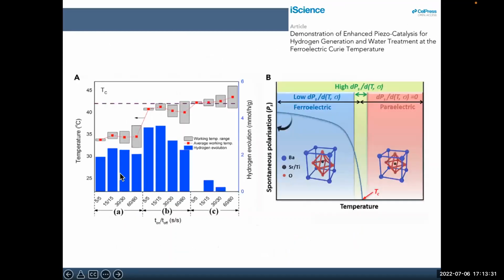So this is BST particles within a solution with the application of ultrasound. And this is just a series of ultrasound conditions where it's on and off, on and off. And by tuning that, we can tune the temperature. So this line here is the temperature. And I think what was nice is that when we get close to the Curie temperature, so when the system is close to the Curie temperature, this is the polarization of the material with temperature.